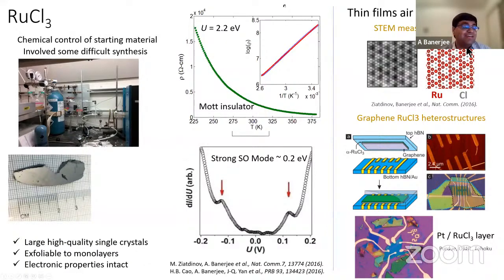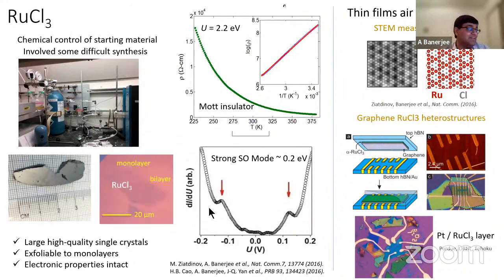And you can do STEM measurements, and you can take Scotch tape and exfoliate this material very nicely, and you can make monolayers. In fact, we have made monolayers and bilayers in my lab. One of my graduate students, Kiran Dikshit, is working on this right now. And we can make heterostructures and devices out of this material. So now we are getting into the realm where we can make quantum electronics out of a frustrated spin-based material. That's a very exciting new territory to be in, because it's completely unexplored.